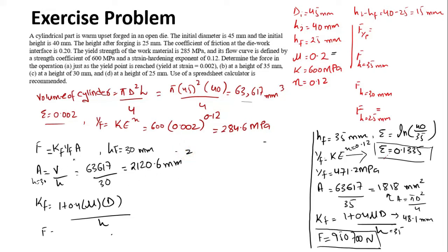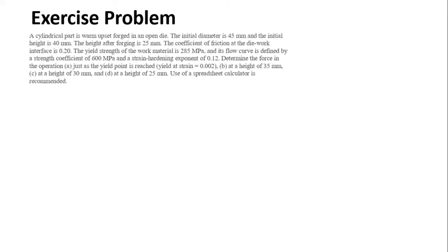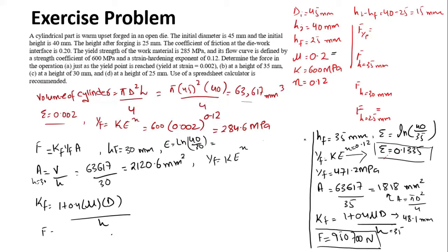Now we can find out the flow stress, so Y equals K strain to the power of the strain hardening exponent, and the strain would be equal to ln of 40 by 30, and that would be equal to 0.2877.